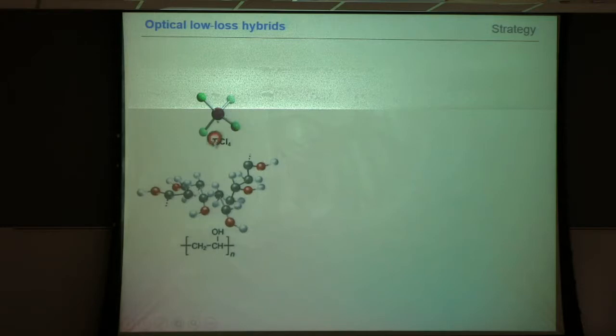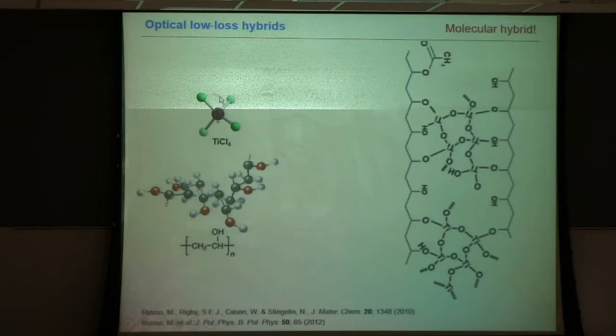Why? Usually this titanium dioxide precursor would interact with itself and actually produce titanium dioxide. But now, in case you have the polyvinyl alcohol around it, these alcohol groups here will interact and actually conduct a hydrolysis with the precursor. So very similar, like in the previous paper I showed, we should actually expect to get essentially a very messy hybrid made up of polyvinyl alcohol chains and titanium oxygen titanium chains with still some end groups from the precursor.